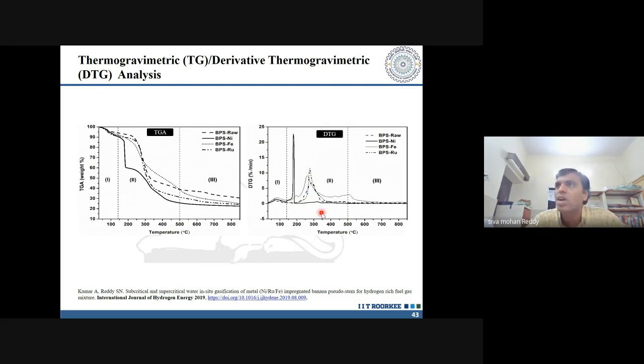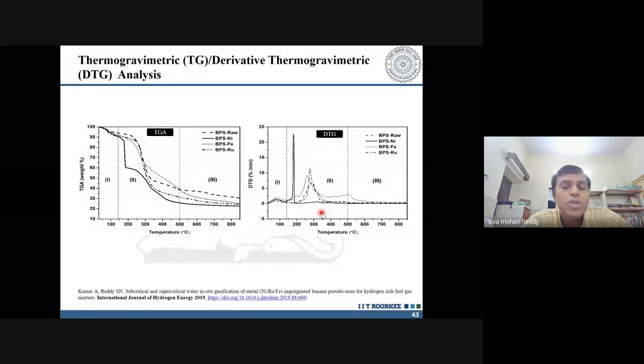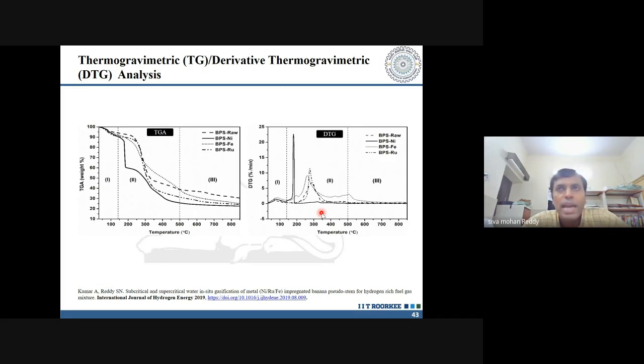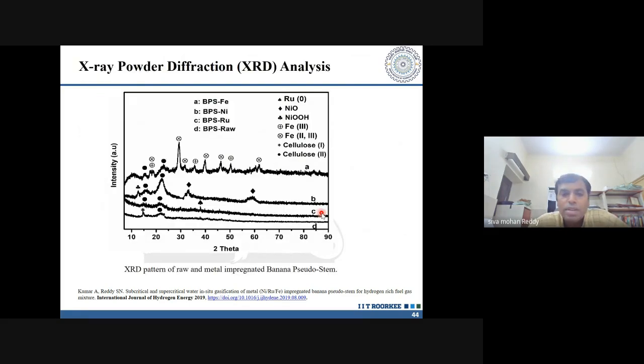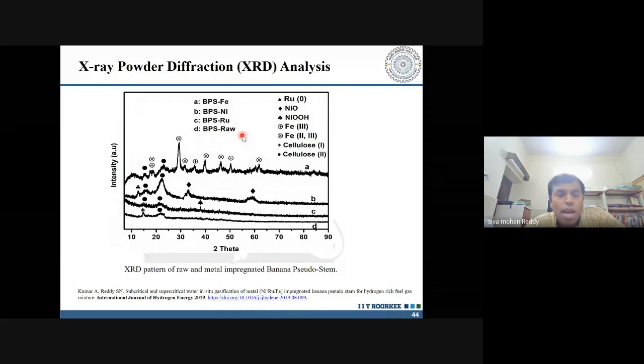So that means it is not only the cellulose, the metal is promoting the degradation of your compounds. And not only that, there is one more reaction that is going to happen, that is the reduction of metal oxides to active nanometals during this degradation process in a single step. So you see that this carbon nanometal composite is going to be converted into carbon nanometal hybrid materials during this hydrothermal treatment.